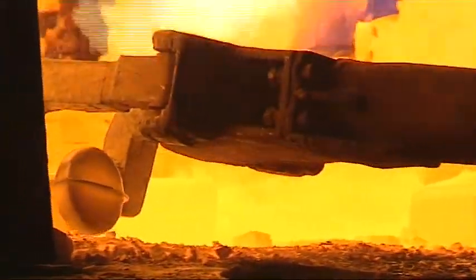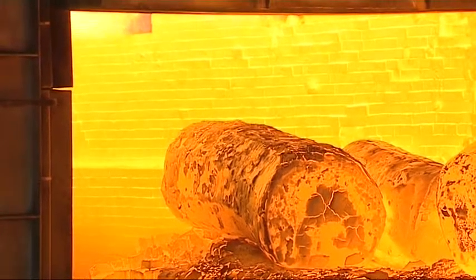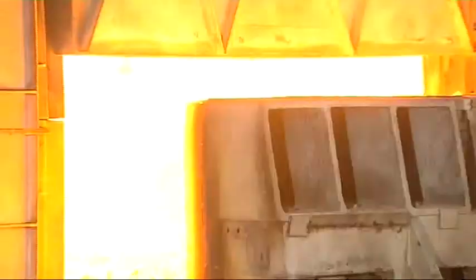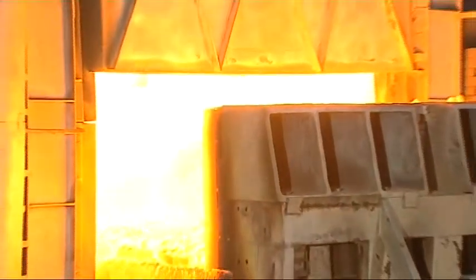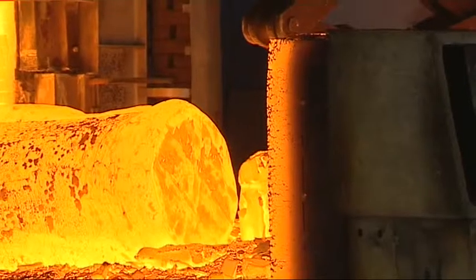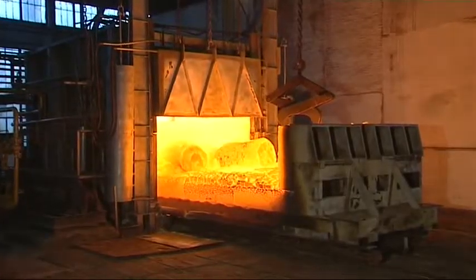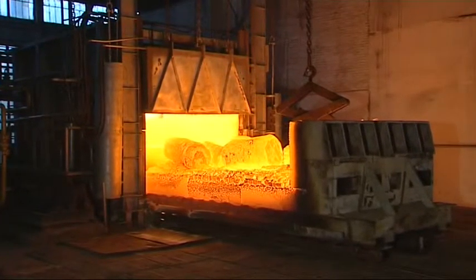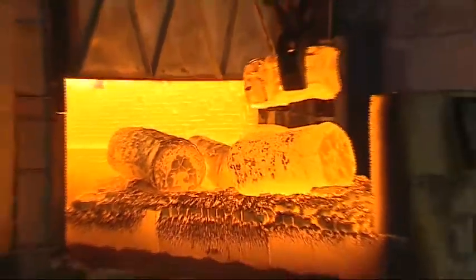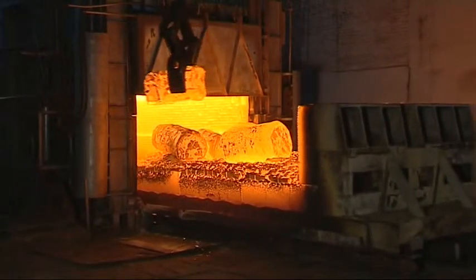Forged and die-forged parts are cooled after forge process within pre-selected mode in the air inside special thermal stabilizing vessels, and then they are delivered for heat treatment in a furnace having movable bottom to impart equilibrium steel structure, increase its plasticity and ductility, relieve internal stresses and therefore significantly improve metal machinability.